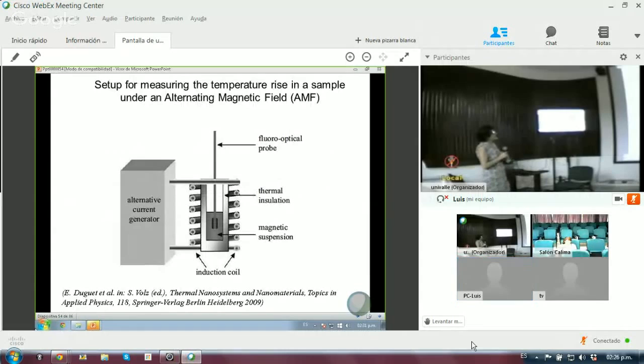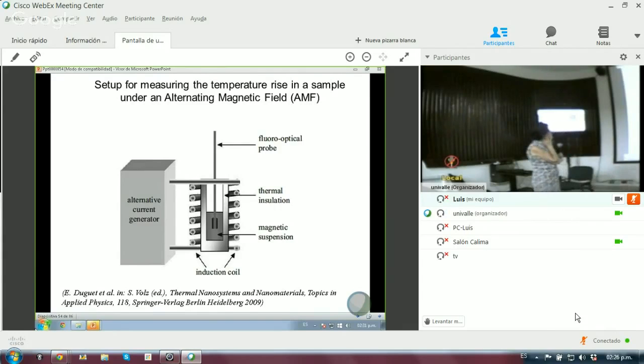Now the next measurements, in this case, she also had to get out of Orléans, which is kind of nice. So we measured with an alternating magnetic field, and there is only one device that we were able to locate in France because it's not something commonly used, and this was in Bordeaux in the team of Etienne Duguet. And this is the schematic of it. It helps in measuring essentially the temperature rise in a sample when we apply an alternating magnetic field. Okay, David, next.